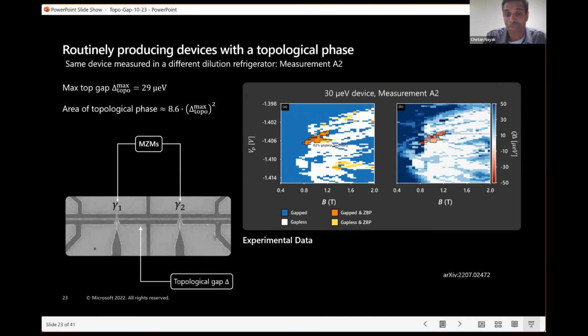We actually measure the same device again. So here's a second measurement in a second cool down. Turns out in this measurement, every time we do a cool down, the disorder of the charge impurities moves around a little bit, so the phase diagram doesn't look exactly the same, but it looks similar. The gap size is similar. In this case, it's about 29 microvolts. The area of the topological phase is again a few times the topological gap squared.